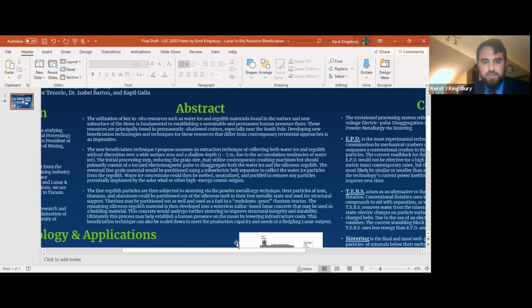The new beneficiation technique I propose assumes an extraction technique of collecting both water ice and regolith without discretion over a wide surface area and shallow depth, which would be between 1 to 5 meters approximately due to the accumulation tendencies of water ice. The initial processing step, which is reducing the grain size, may utilize contemporary crushing machines, but should primarily consist of a focused electromagnetic pulse to aggregate both the water ice and the siliceous regolith. The eventual fine grain material would be partitioned using a triboelectric belt separator to collect the water ice particles from the regolith.